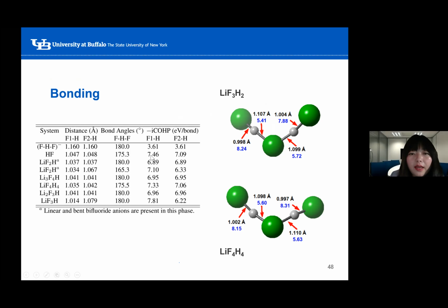Comparing to the HF bonding in the one-dimensional HF zigzag chain of the HF phase, we find that the HF bonds in the bifluoride anion of the ternary phases would be shorter, but also weaker. That's suggesting that the complicated chemical environment of the ternary phases is destabilizing the anions. So we also took the trifluoride anions out of these 2 phases and analyzed them. As we expected, it is agreeing with the ambient model that the terminal FH bond would be stronger and shorter, and the middle FH bond would be longer and weaker. So it can be viewed as 2 FH interacting with the middle F minus.